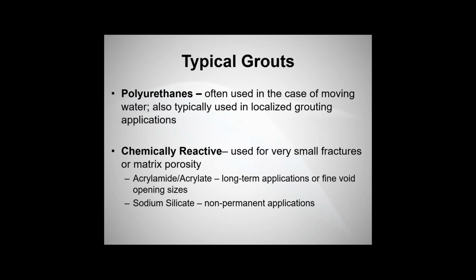Polyurethanes are also used in the case of moving water, but from a sheer cost and volume perspective, they're typically only used in localized grouting applications for the most part. If you've got a large volume, large area, more than likely you're going to go to one of the other ordinary Portland cements, ultrafine cement, or a chemically reactive if it's the right application. Again, chemically reactive, they're used for very small fractures or matrix porosity. Acrylamides and acrylates are long-term applications or fine void fill opening sizes. Sodium silicates, again, are considered temporary or non-permanent by most in the industry.